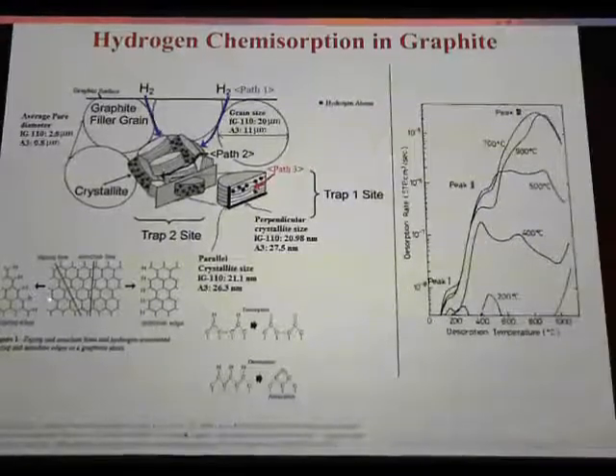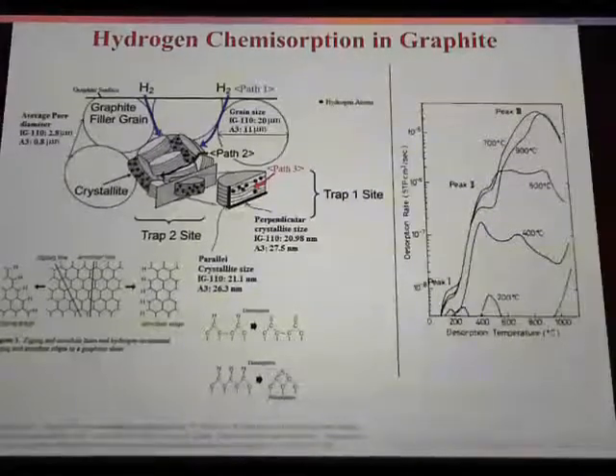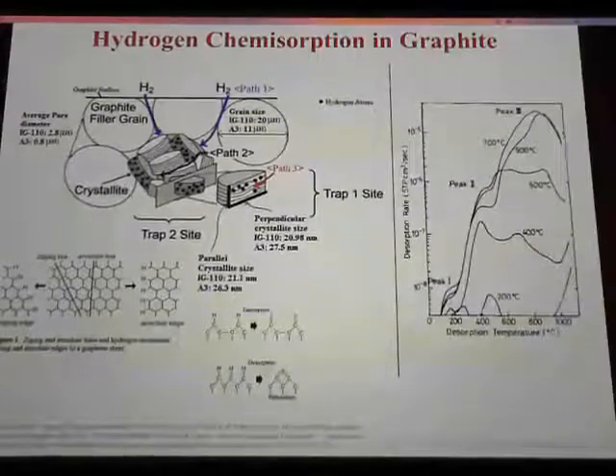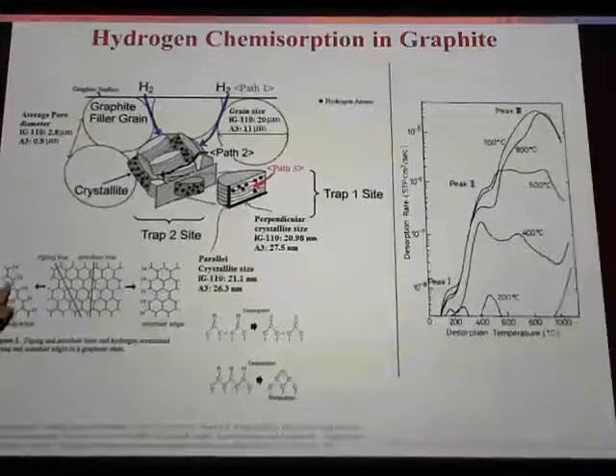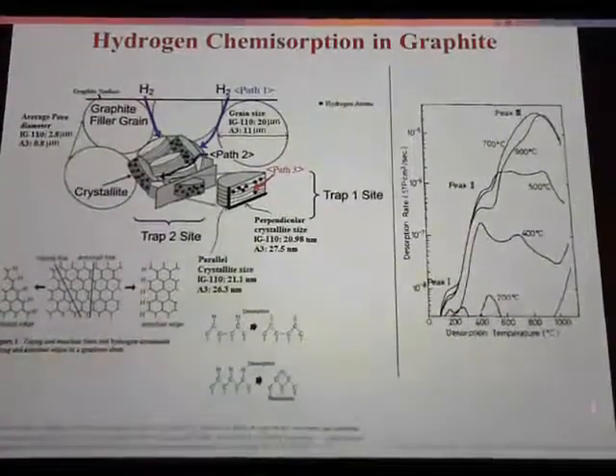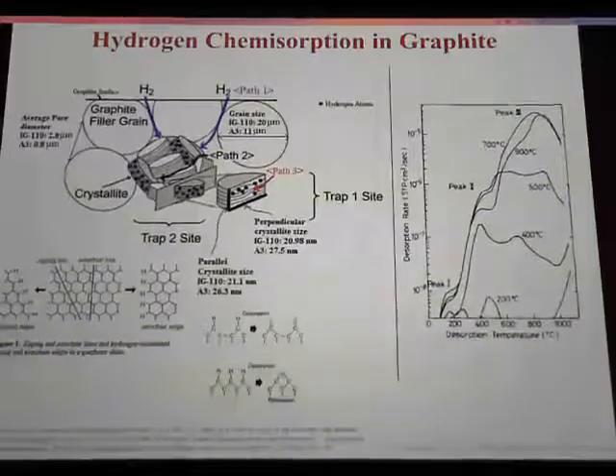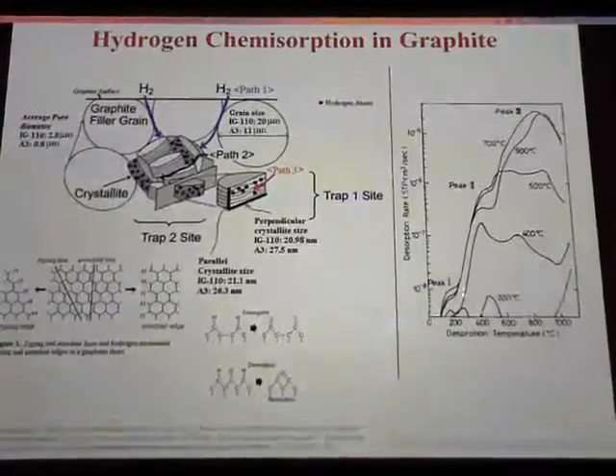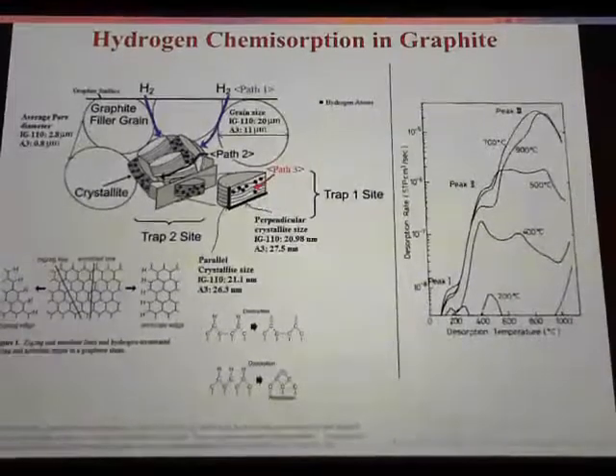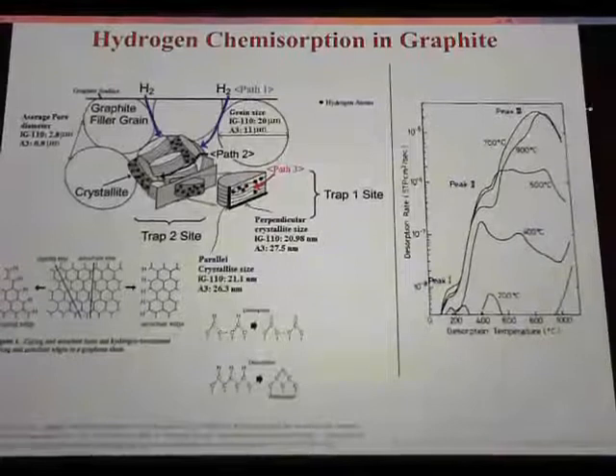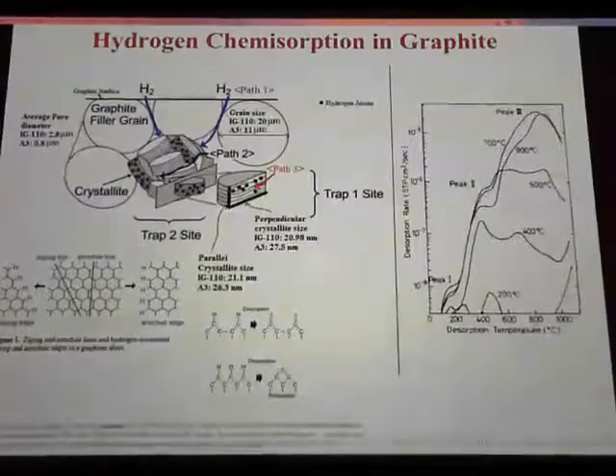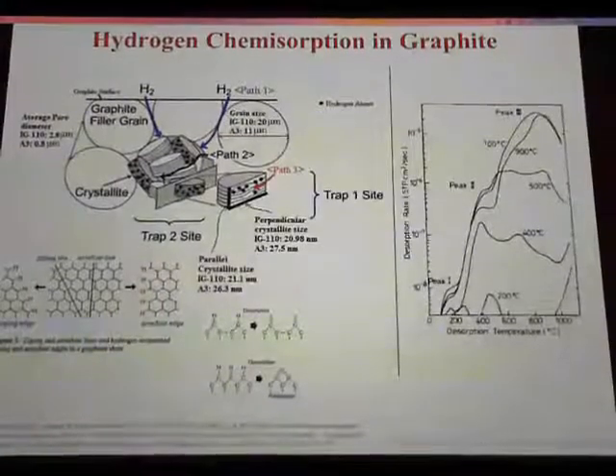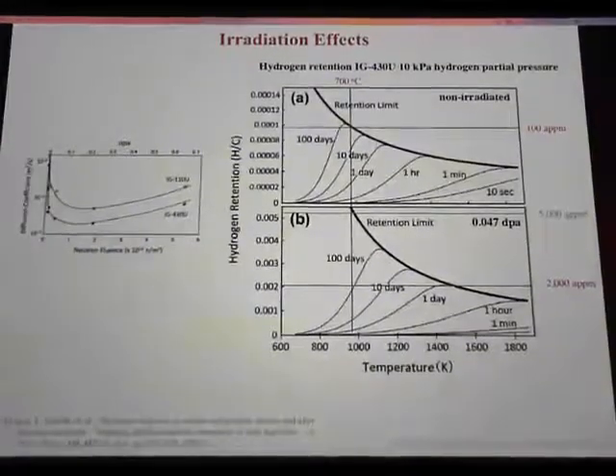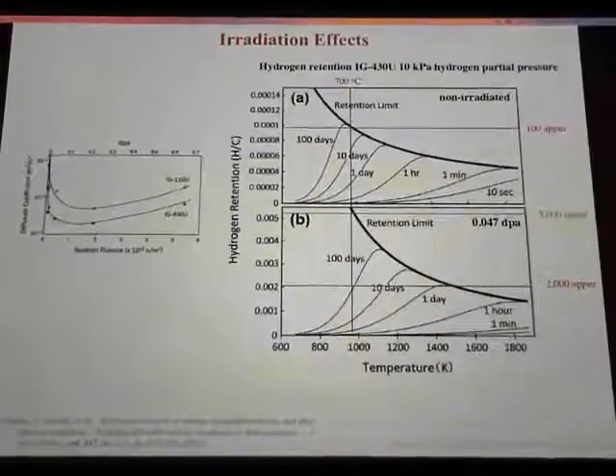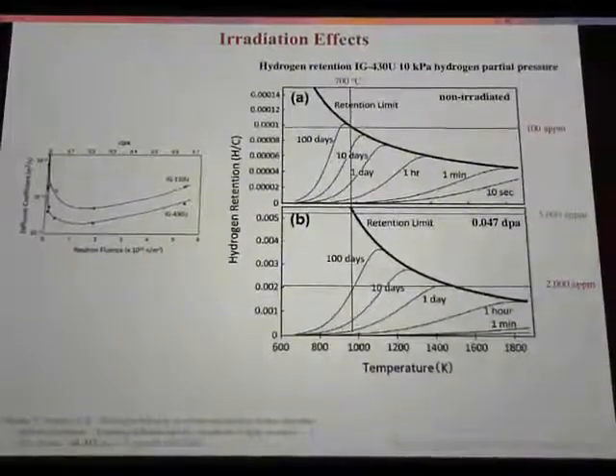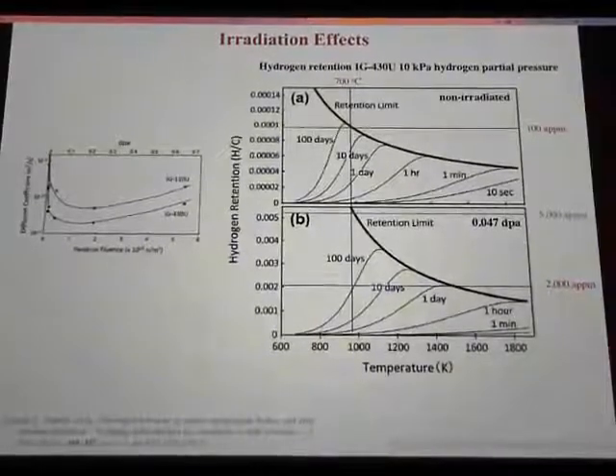Okay. So one way that the behavior of these traps has been studied is with thermal desorption analysis. And so a graphite that's been exposed at 700 degrees Celsius has desorption peaks at various temperatures which correspond to different types of trapping sites that have different energies. So we care about that because we want to have a chemical transport model for hydrogen moving into the graphite so that we can match that profile that we saw in the MSRE.